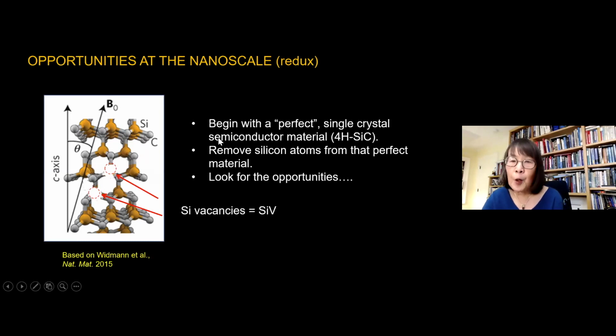We begin with a perfect single crystal semiconductor material. But now what we're going to do is disrupt that perfection. We're going to remove silicon atoms from that material. So we create what I call silicon vacancies here and here. And having insulted the material in this way, we're now going to look for opportunities. So this picture that I've given you of our starting material, vacancies in silicon carbide, perhaps is the wrong way to look at the problem.